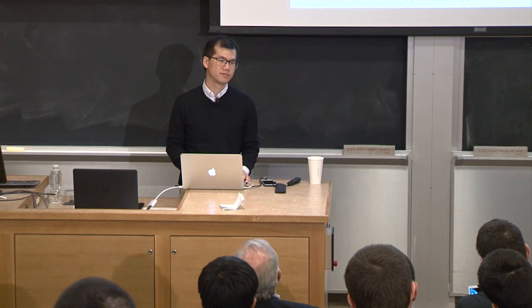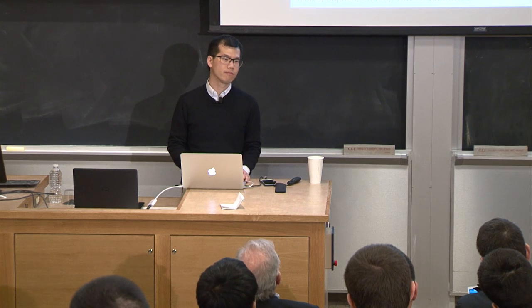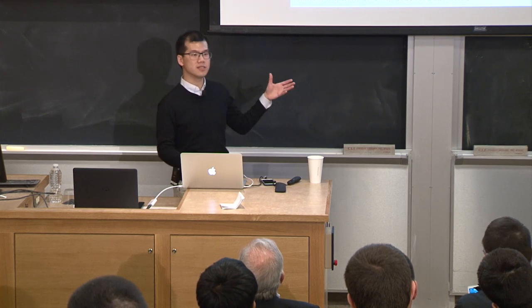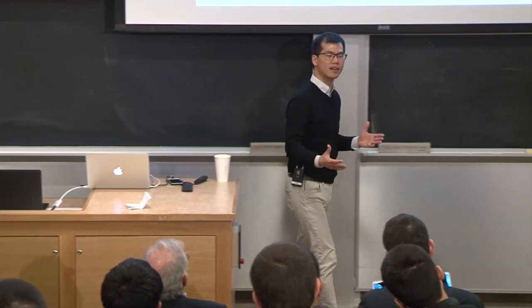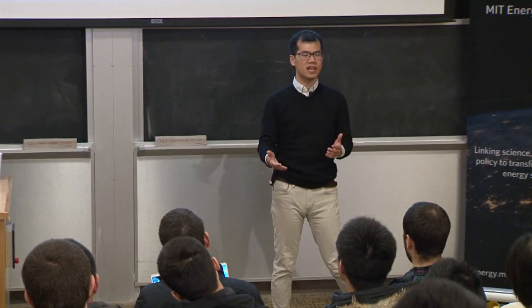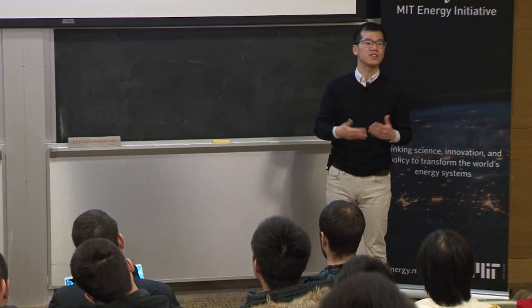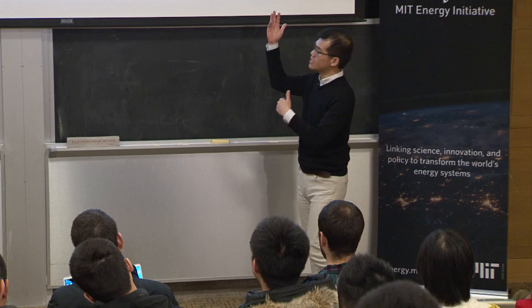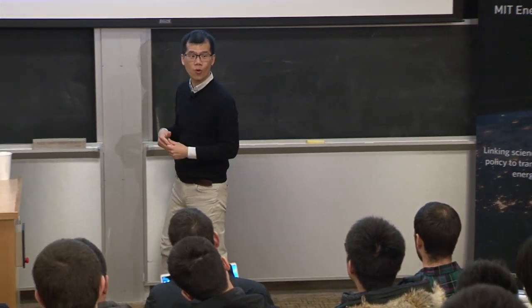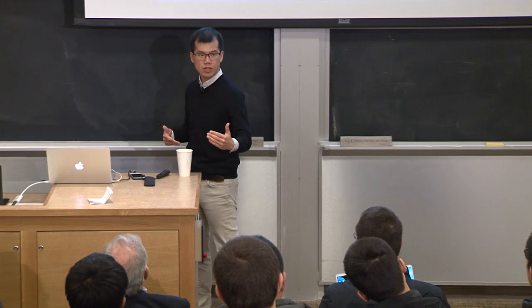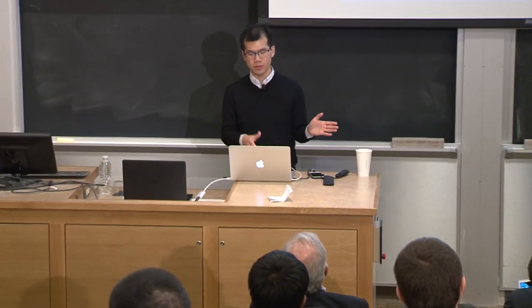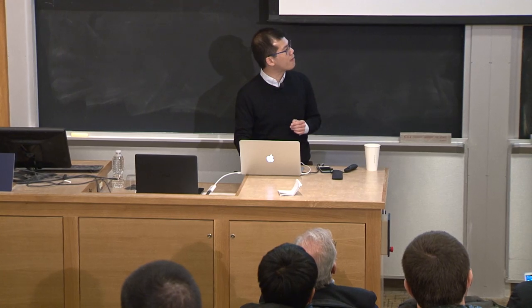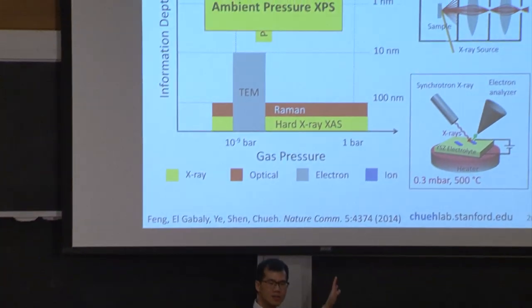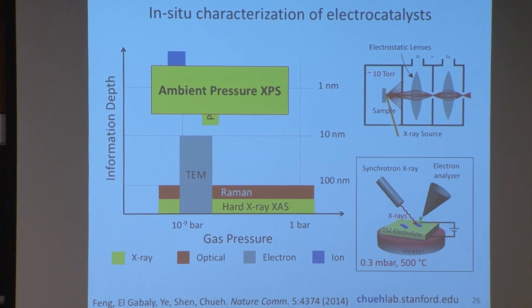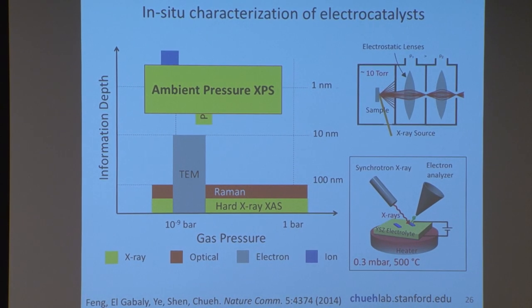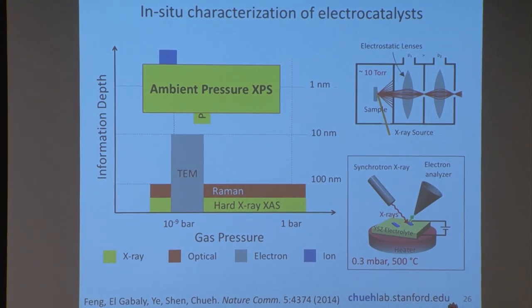Is there any complication coming from the high temperature when doing the XPS? So these reactions in the electrochemical cell run at practically about 700 degrees Celsius. So in this case, we also ran our in situ experiment at the same temperature. And the reason is because as you change the temperature, the adsorption free energy changes accordingly. So it's important to be at the temperature you're interested in. The only drawback is that we weren't able to use a very high pressure. So the pressure was only about a few millibars, under a millibar. So it's still very far from 1 bar. It's getting closer, but not quite there. So there's still a gap. But I think this is a lot better than doing this in vacuum.